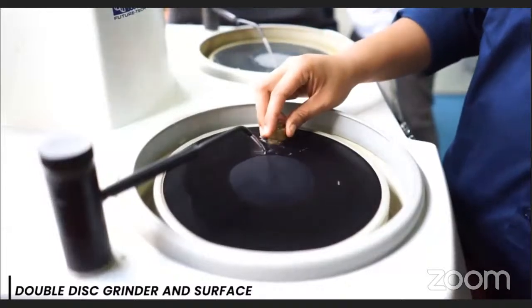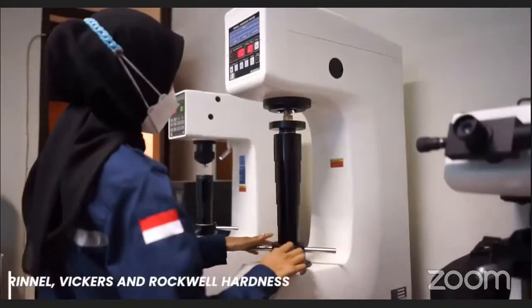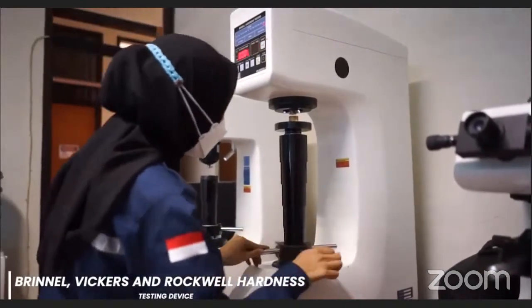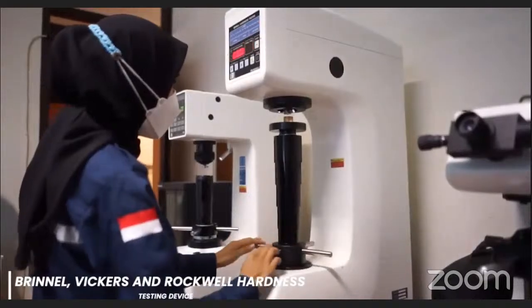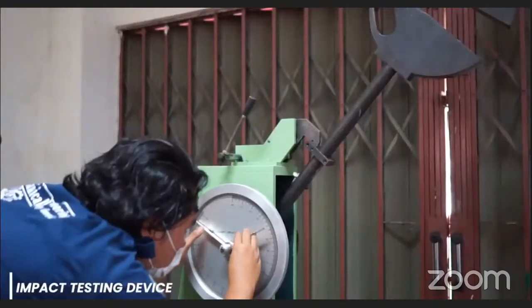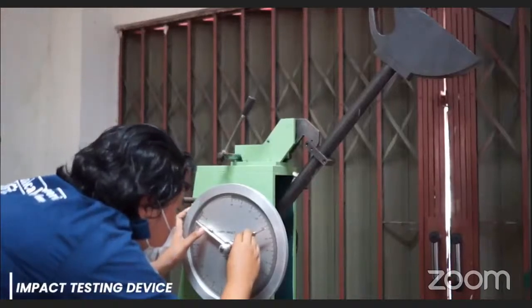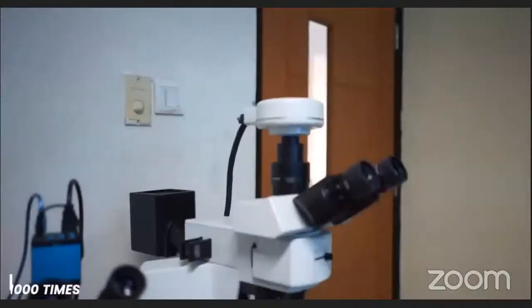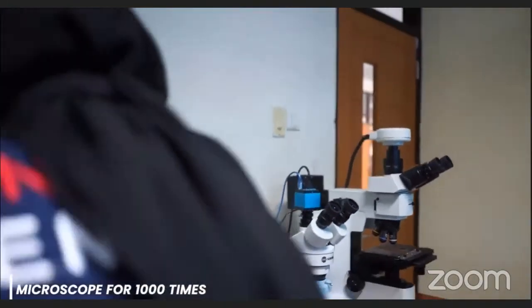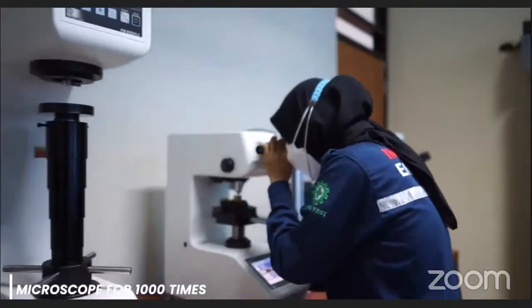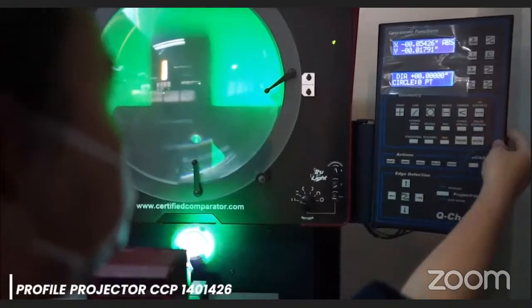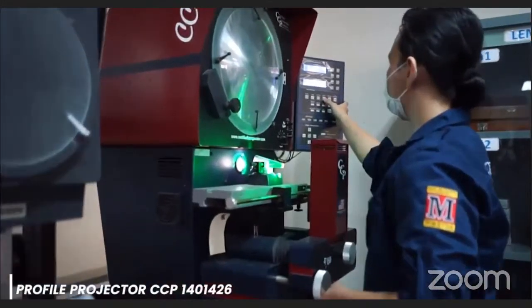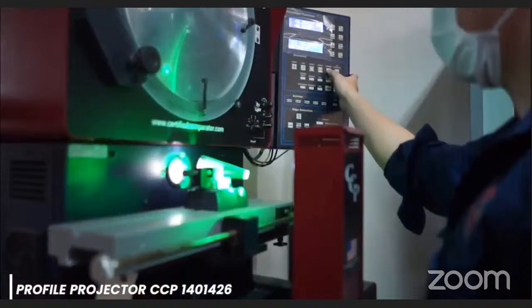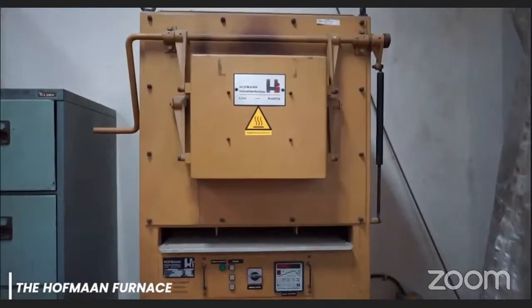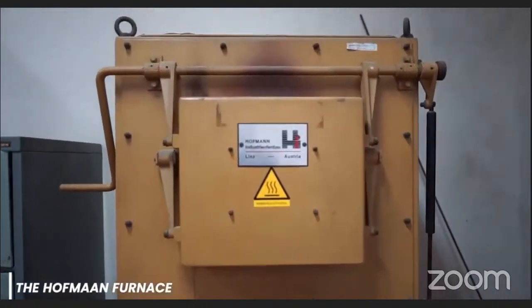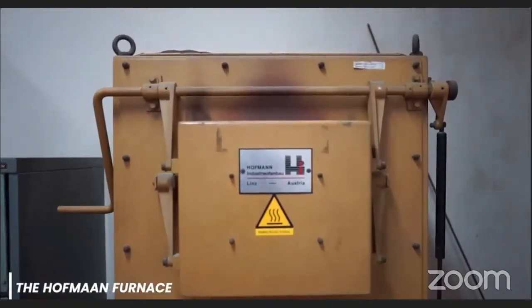Double disc grinder and surface polisher with adjustable rotating speed. 2. Brinell, Vickers, and Rockwell hardness testing device with a maximum capacity of 3000 kg force. 3. Impact testing device with a Charpy method and a maximum load of 800 kg force. 4. Microscope for 1000 times magnification. 5. Profile projector CCP 1401426 for 20 times magnification. 6. The Hoffman furnace with a maximum temperature of 1000 degrees Celsius.